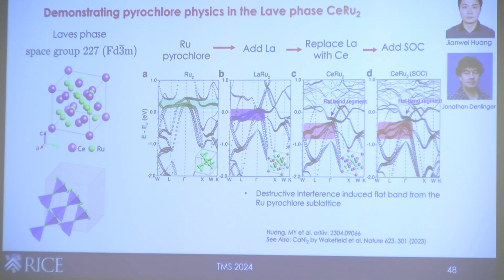First, he calculated just the pure ruthenium pyrochlore sublattice, and these highlighted in green are the flat bands associated with this destructive interference in 3D. And then next step, he added in the lanthanum, which is basically the same structure, but without the f electrons. And you see the evolution of the pyrochlore flat bands captured here. And then he replaced them by cerium, and then eventually added SOC, so that you can trace that these bands that you calculate with DFT originate from the pyrochlore flat bands associated with the ruthenium sublattice. There is some bandwidth that's gained, but there are portions that are still flat, and experimentally we look for those.